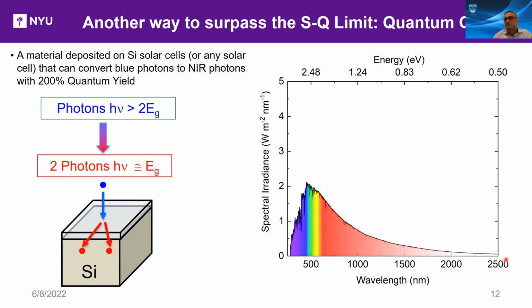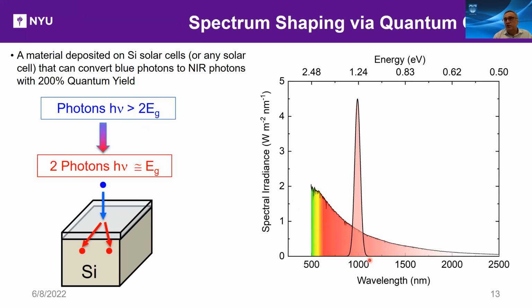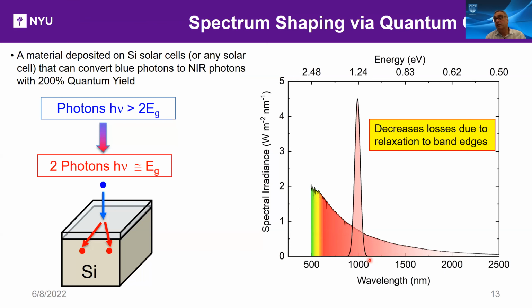Here I show, for example, the spectral irradiance of the sun. And you can see that here, and I left a lot of room here. What we're going to do is take all the UV and blue light here and convert them to near infrared photons at the band edge of the silicon, about 1.1 eV. It turns out that for the material system that I'm going to talk about, the emission is at 1.24 eV, but it's very, very close. So this is what we're trying to do. Take all those photons and lump them into near infrared. And hence the sort of provocative title, Changing the Sun. So what we send into the solar cell is not this, but this, so that we avoid heat losses due to relaxation to the band edges.